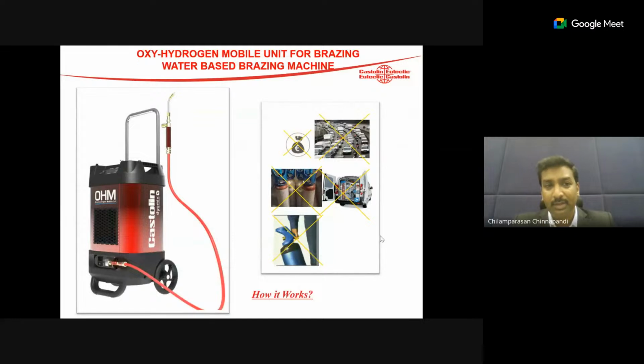Now we have the oxygen hydrogen mobile unit where brazing can be done without any gases. You may ask, how is it possible to do brazing without gas? In this process, this equipment uses distilled water as a fuel, just distilled water. What is happening is that the water is separated into oxygen and hydrogen, and you get the hydrogen flame. And a hydrogen flame doesn't have any odor or smell or color. So at the end of the tip, you just get color or smell by adding an additive such as acetone. That is just an add-on. It is nowhere connected with the process of getting this hydrogen flame.